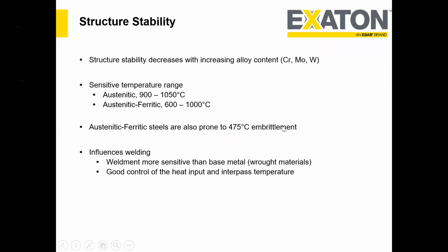Now, structural stability, which is very, very important for the duplex. And this is one of the real challenges during the fabrication of duplex. These three alloy elements are helpful, but at the same time they also have a detrimental effect on the structural stability. So structural stability decreases with the increasing amount of chromium, molybdenum, and tungsten. Later we have a graph, I'll show that.